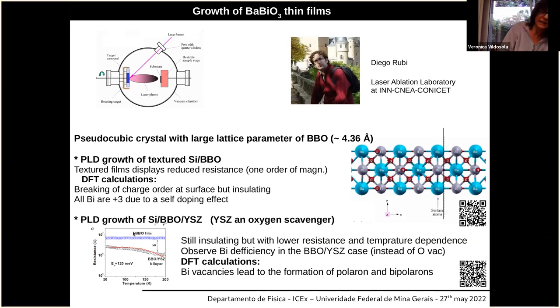And they studied the transport properties of this film, and they observed that when the system has yttrium stabilized zirconia, there is some resistance that depends on temperature, as if there were some defects, some diffusion mechanism of defects. And we studied the system with DFT calculations and observed that the bismuth vacancies lead to the formation of polarons and bipolarons, and the energy barriers of the diffusion of these polarons can explain the behavior of this material. But okay, no 2D metallic states at any surface.